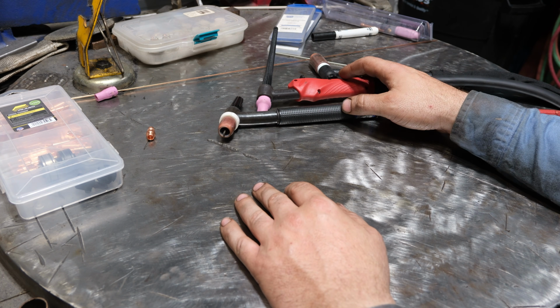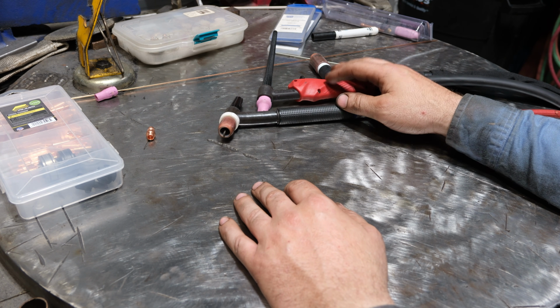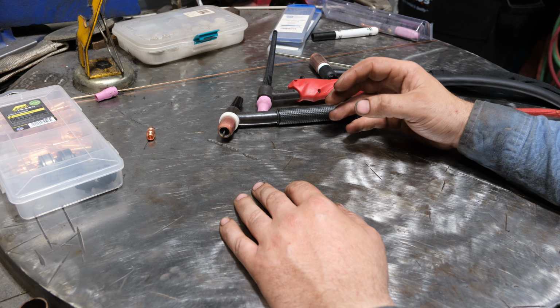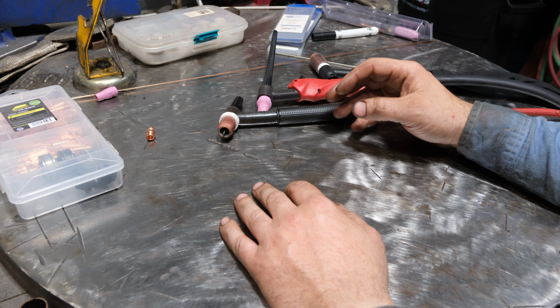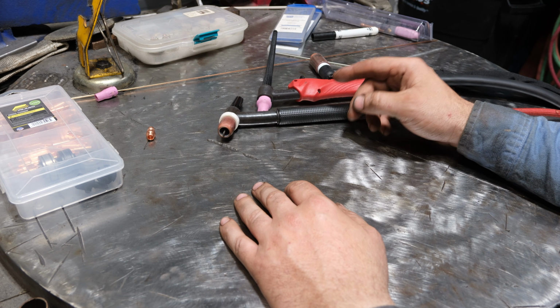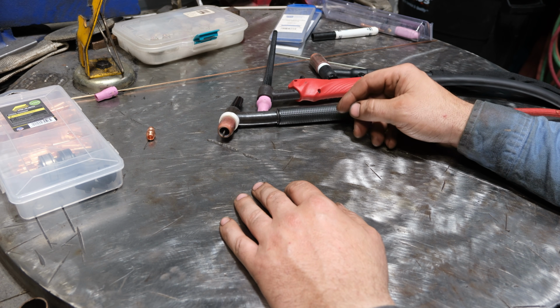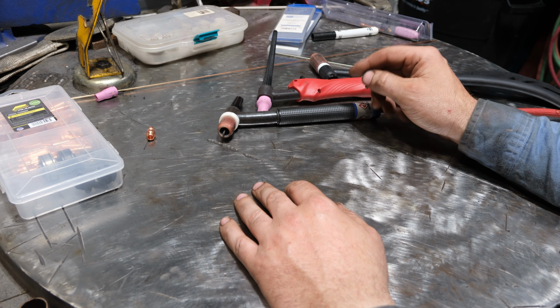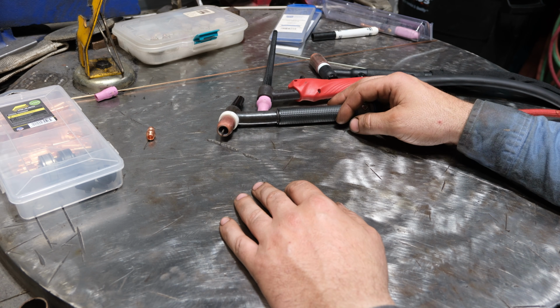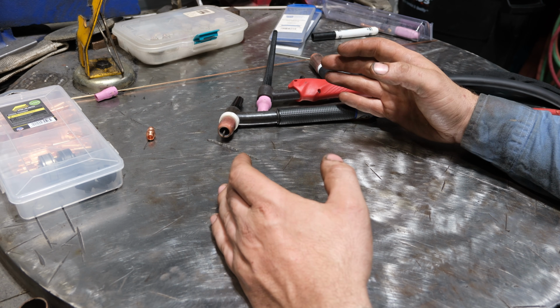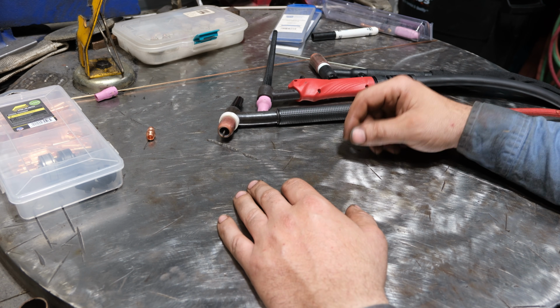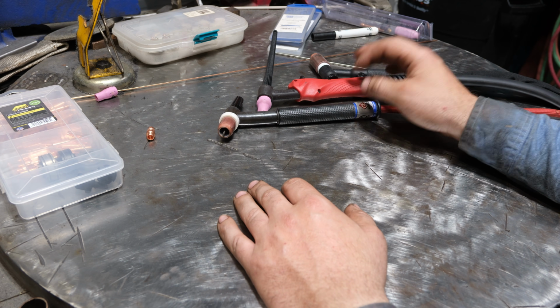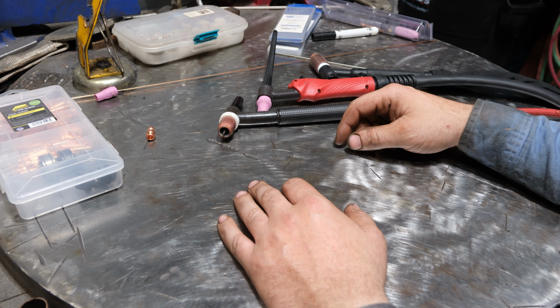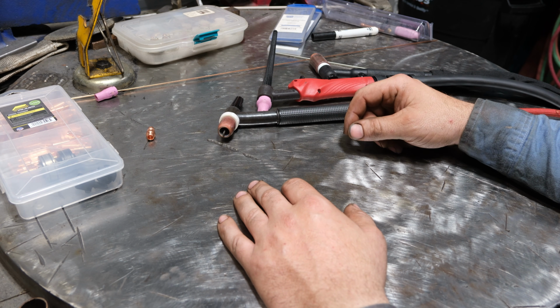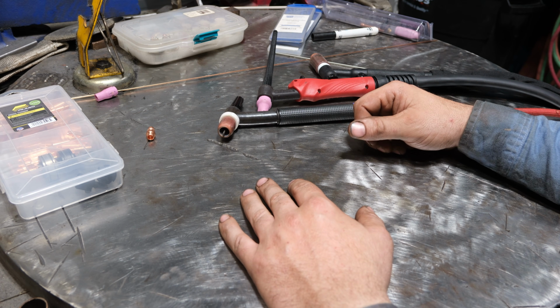Now, speaking of other benefits, there's actually a lot of them with the process. If you want to weld thin material, so 3.2 millimeter or 1/8 inch or thinner, TIG is exceptionally good at that. You can weld 26 gauge or smaller material with TIG, versus a lot of the other processes like stick, where it's impossible to weld 22 gauge. Good luck. The ability to weld aluminum with the same tank as steel is also a cost savings if you buy an AC machine, so that is also a huge benefit.